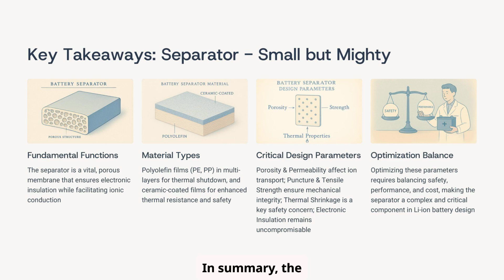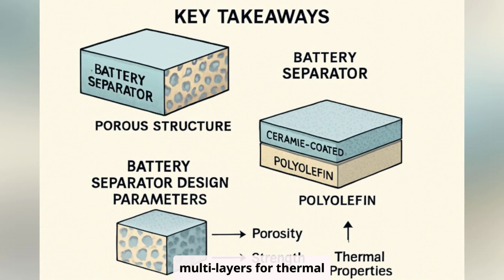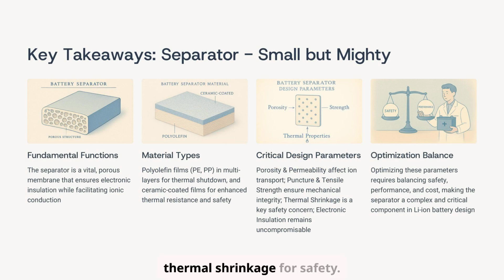In summary, the separator, though small, is mighty. Its fundamental functions are ensuring electronic insulation while facilitating ionic conduction. Material types range from polyolefin films, like PE and PP, often used in multilayers for thermal shutdown, to ceramic-coated films for enhanced thermal resistance and safety. Critical design parameters include porosity and permeability for ion transport, puncture and tensile strength for mechanical integrity, and managing thermal shrinkage for safety. Ultimately, optimizing these parameters requires a delicate balance between safety, performance, and cost, making the separator a complex and critical component in Li-ion battery design.